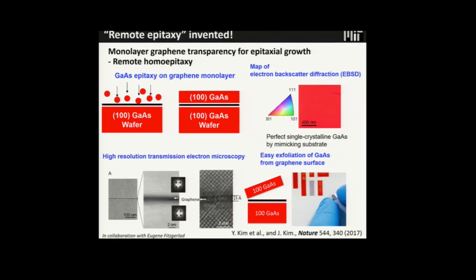The reason is that if the underlying substrate becomes the seed layer, then you can copy-paste underlying substrate through monolayer graphene, meaning that you can give me any type of extremely expensive wafer. That's fine. We're going to have one monolayer graphene. We can copy-paste this epi layer from the substrate. We can do the epitaxial growth through the graphene, so then you can keep reusing your substrate.